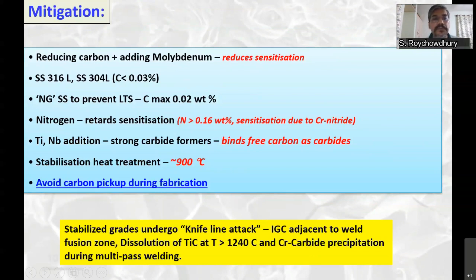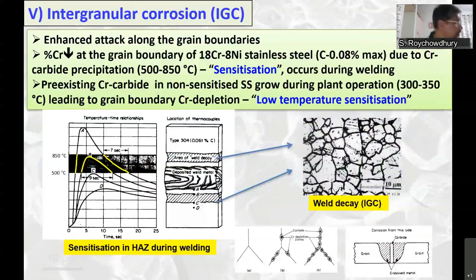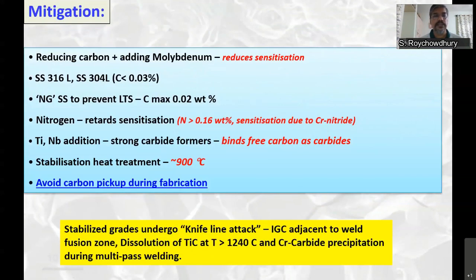So what is the advantage? If you have a very low carbon to start with, and you have any pre-existing carbide but non-sensitized stainless steel, then during normal operation in the temperature range of 300 to 350, these carbides will grow over a period of time, say 10 to 15 years, and finally lead to sensitization. So this is called low temperature sensitization, where no new carbides precipitate, but pre-existing carbides will grow. For such LTS, further lowering carbon minimizes that chance also.